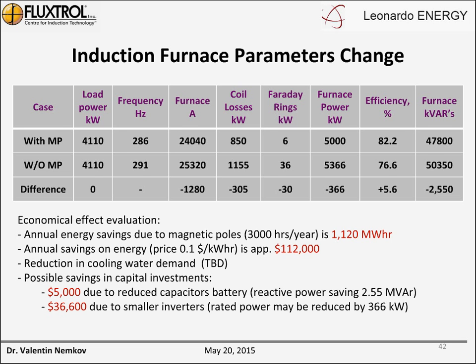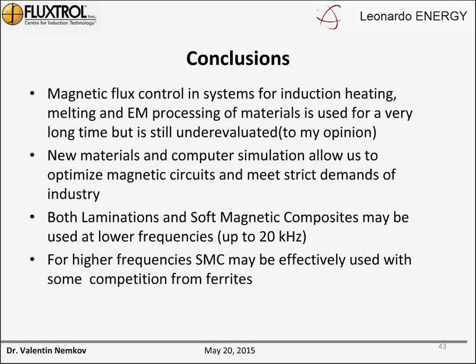And conclusions. Magnetic flux control in systems for induction heating, melting, and electromagnetic processing of material has been used for a very long time, actually, but it's still, in my opinion, under-evaluated. New materials and computer simulation allow us to optimize magnetic circuits and meet strict demands in the industry and optimize the overall performance of installations. Both laminations and soft magnetic composites may be used at lower frequency, up to 20 kHz. For higher frequencies, soft magnetic composites may be effectively used, with some competition from ferrite.